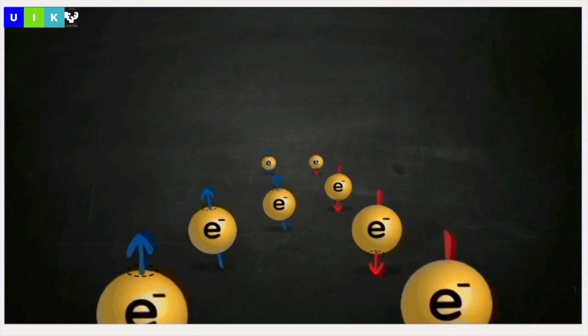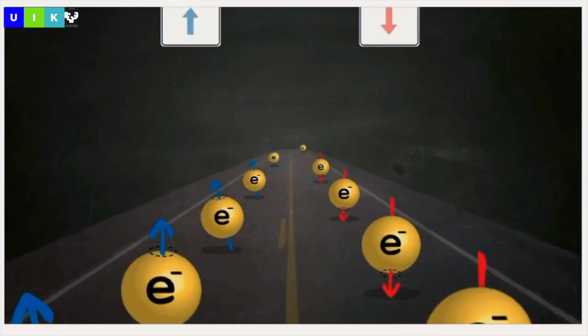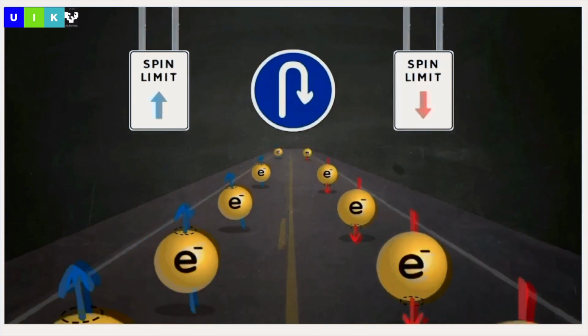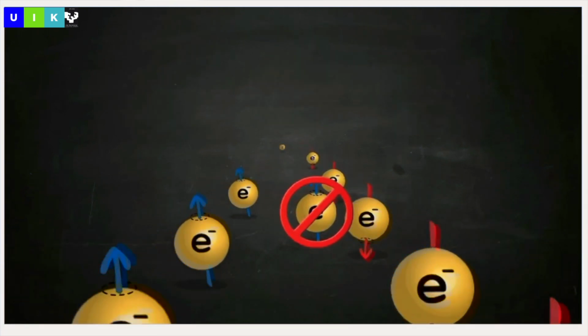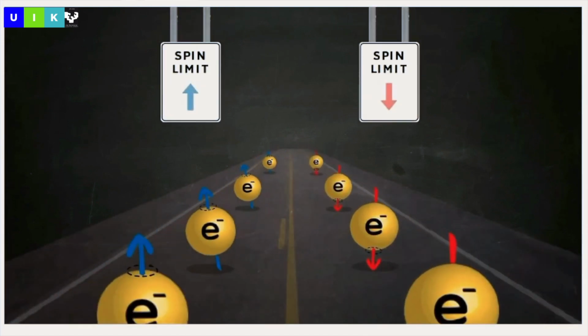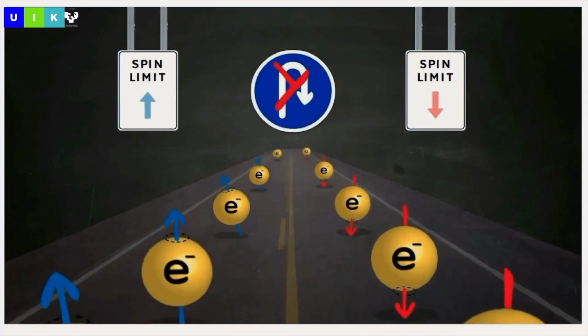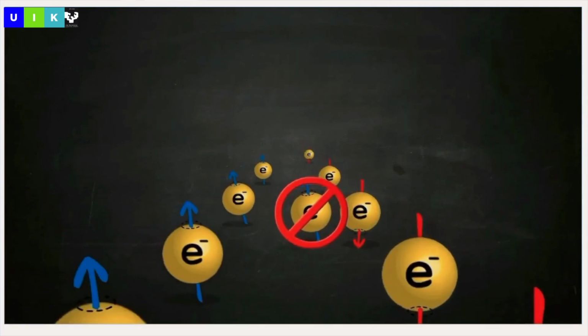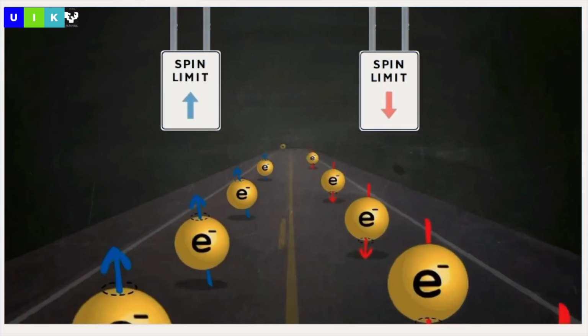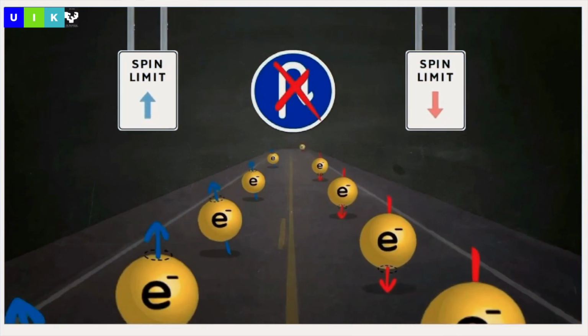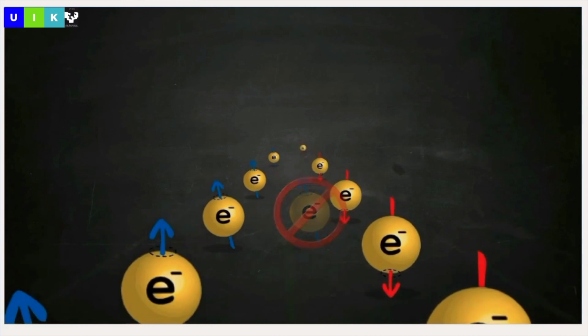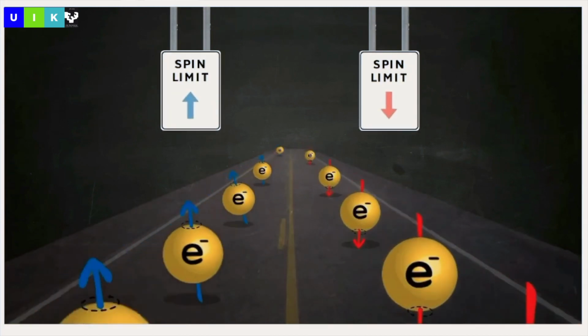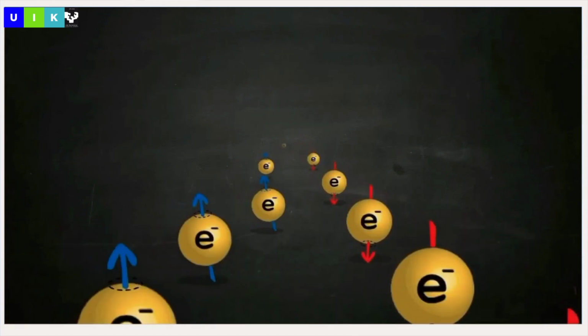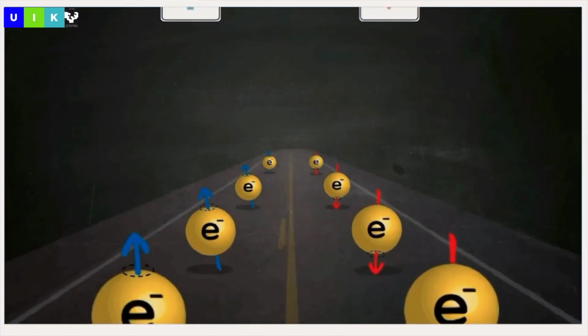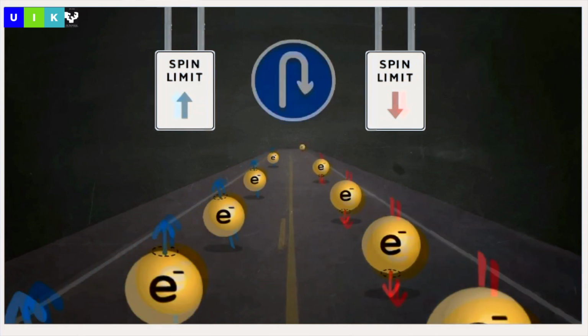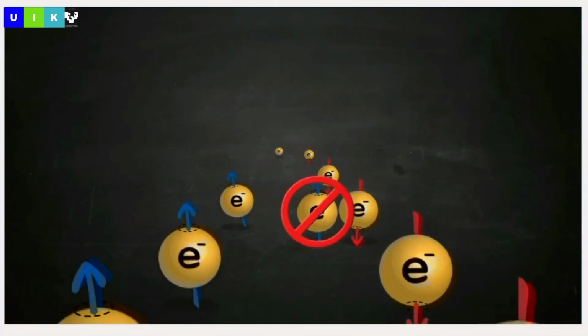Okay, and this is very nice because if spin and momentum are locked, we have this protected surface state, so they cannot be backscattered. So theoretically, we should have fantastic spin polarized currents, which would be then very, very nice and interesting for electronics. And the first proposal here was that people thought we have a problem if we make computers, to connect the different parts of the computers, the interconnects, and if you have these really highly conductive, even spin polarized currents, you might have a totally new electronics area.